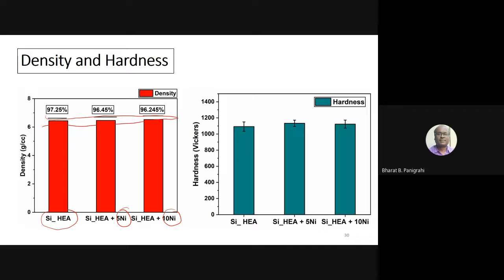That is fine. When you look at their hardness, since nickel is a softer phase, but you can see their hardness does not change drastically because the base alloy is already a harder phase, and nickel being a softer phase, we expected a change, but it did not change. The hardness is retained without really compromising it.